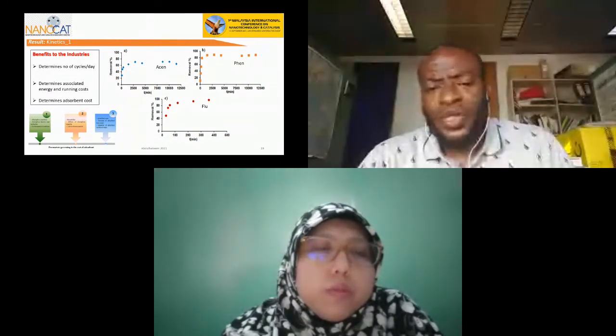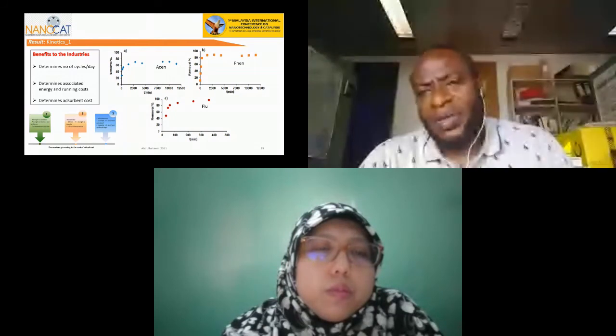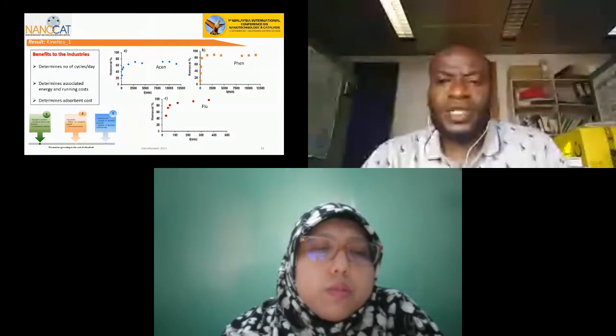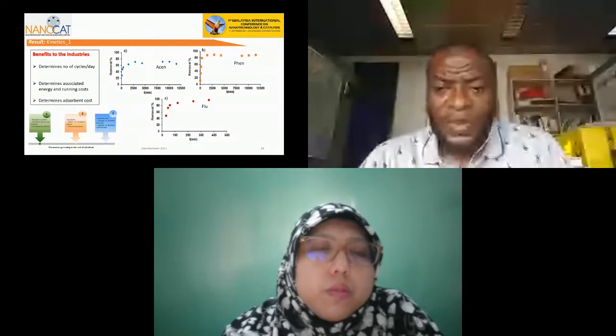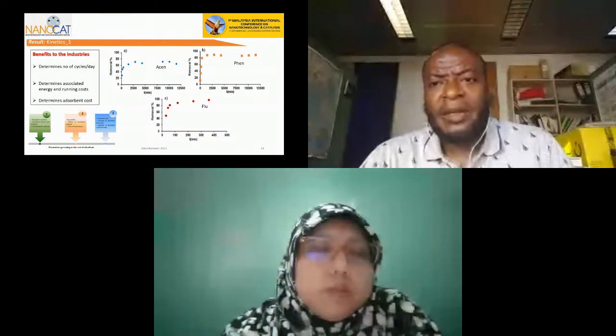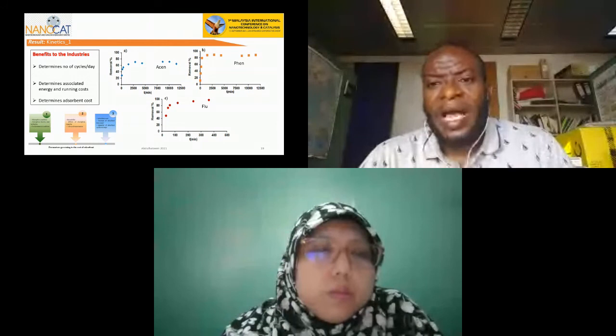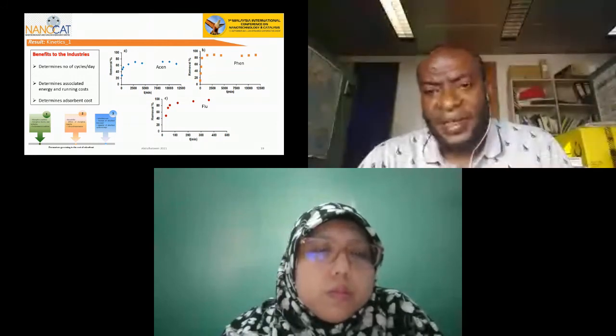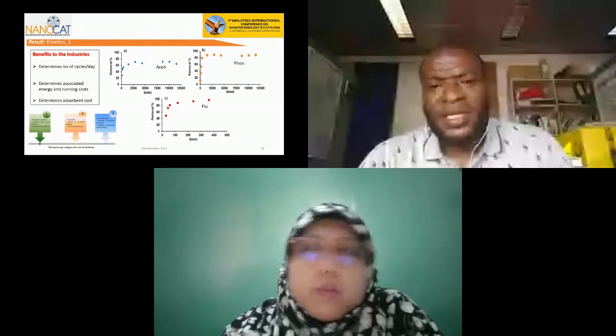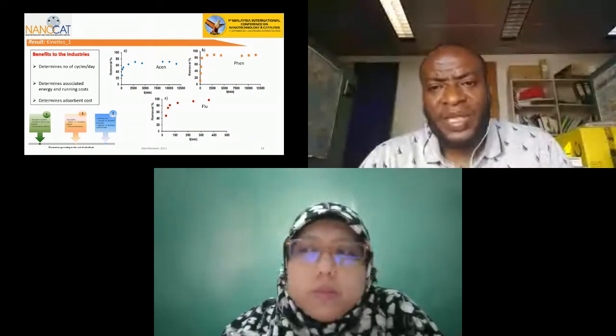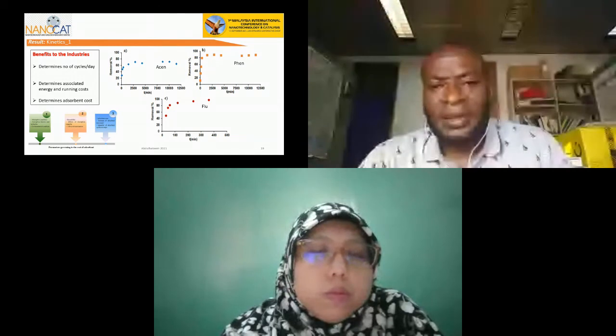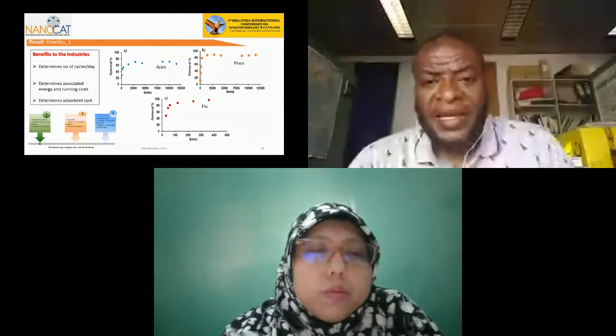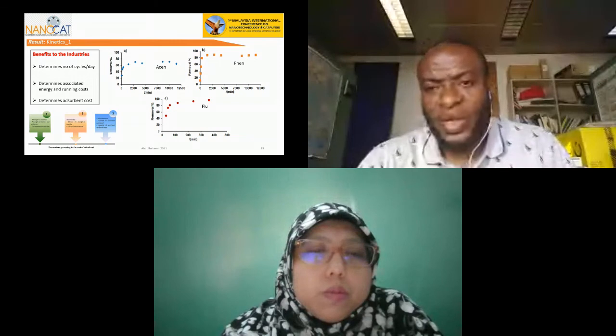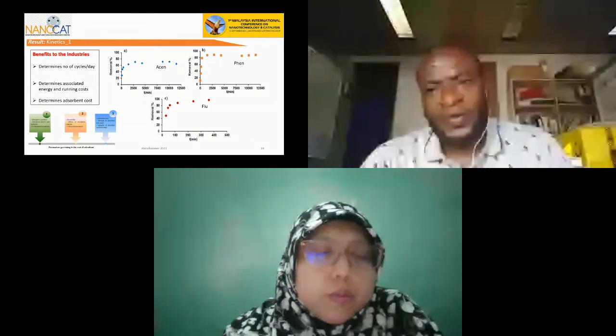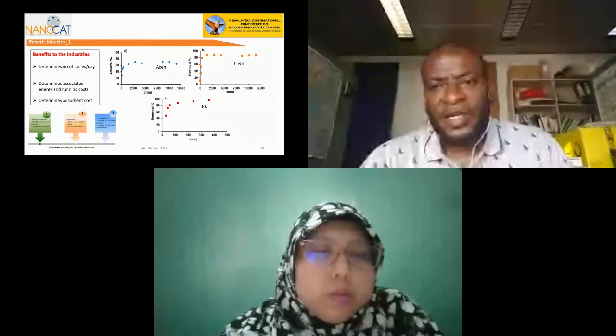A possible explanation for this is the structure of these compounds. We do know that fluoranthene has the highest number of rings among the 3 compounds. Therefore, there is more possibility for them to have a high number of interaction sites to interact with the adsorbent. This may be responsible for the highest removal efficiency witnessed by fluoranthene. The next in line is phenanthrene, then the last one is acenaphthylene, in that order.